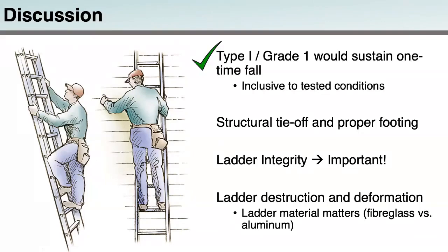Secondly, it's also important to note that we found that the destruction and deformation to the aluminum ladders was a lot more obvious in comparison to the fiberglass. The failed rung on the fiberglass ladder was actually quite surprising. While we had seen some slight cracking in the fiberglass around the rung, it wasn't obvious that the ladder was about to fail until the test was carried out. In comparison to the aluminum ladder, where it was very obvious and clear that the structural integrity of the ladder was being compromised with the drop tests.